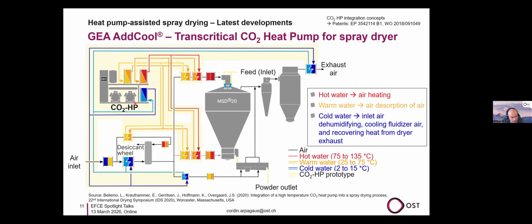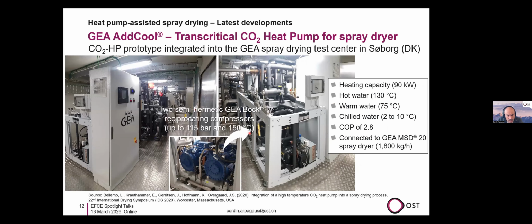And then on the cold side of the heat pump, there is the possibility to use the exhaust air of the spray dryer as a heat source to recover this latent heat, or to use the cold side also as a cooling water loop. So both sides of the heat pump, the hot and the cold side, would be useful in this case. This is an installation at the test center from GEA in Søborg, in Denmark, close to Copenhagen.